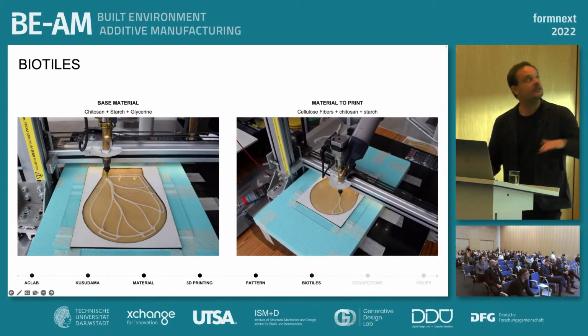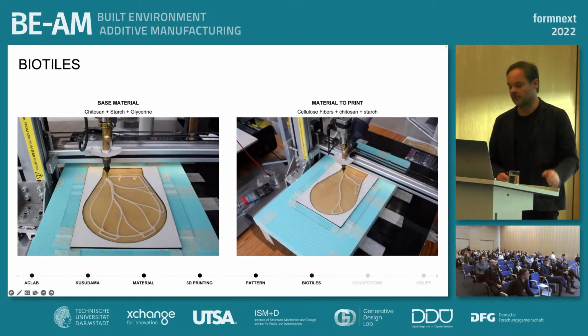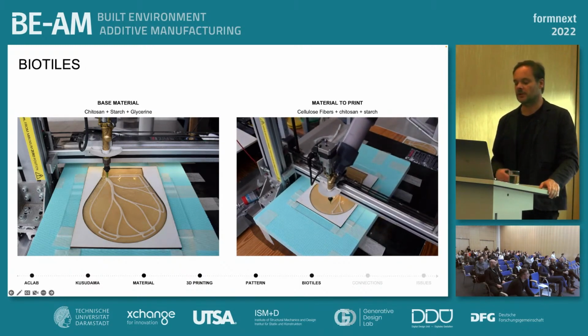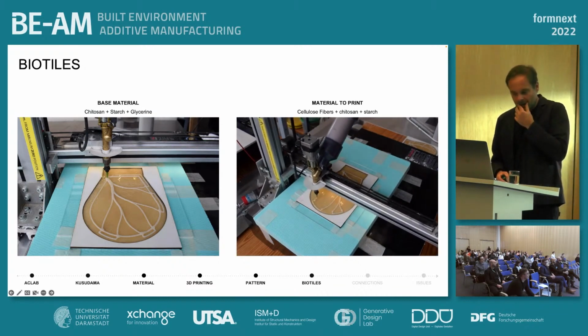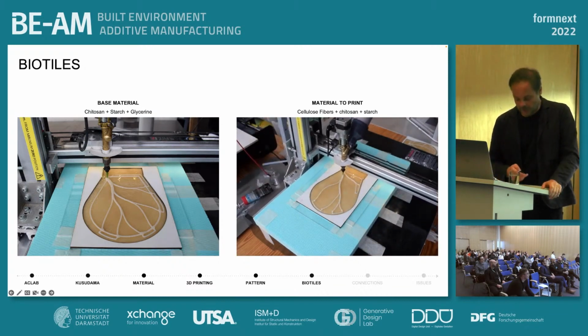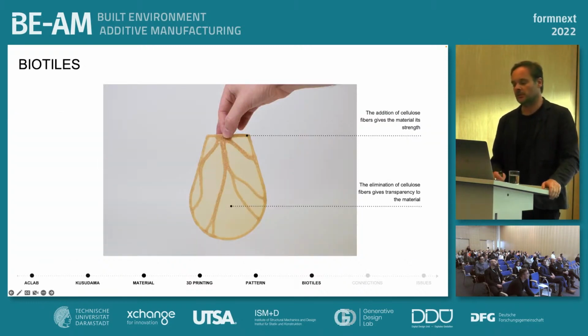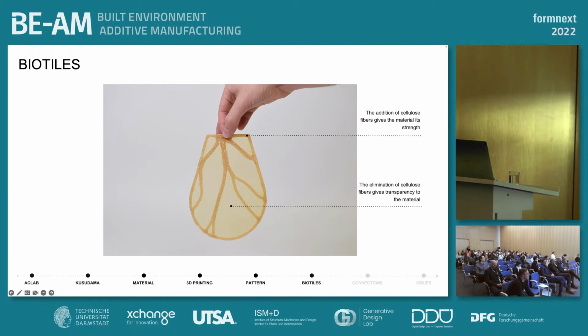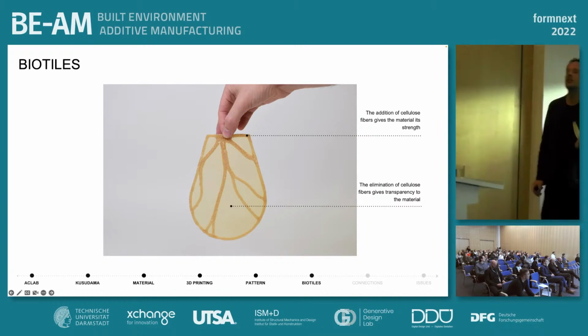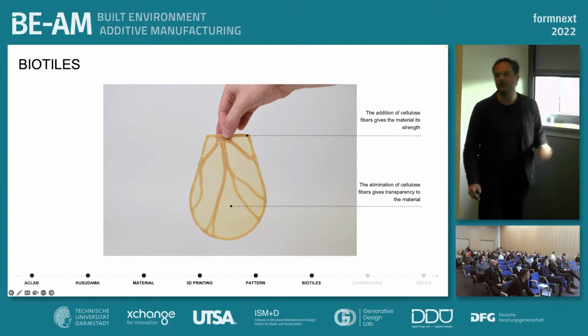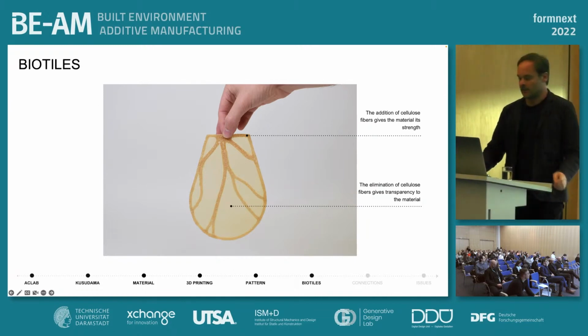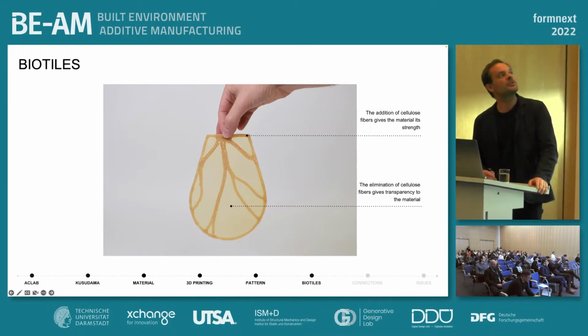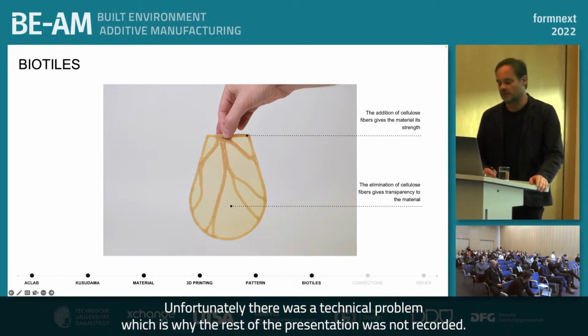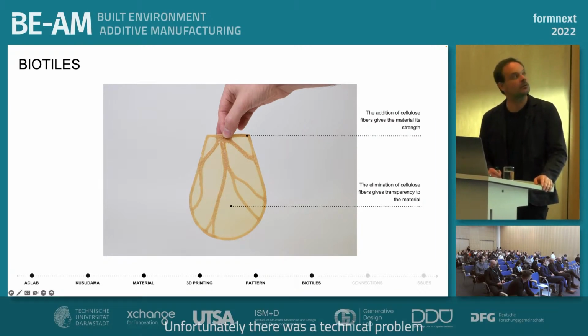And you see here the base with liquid mixture, and then printing the fibrous mixture with cellulose above it. And eventually, when all stages are completed successfully, the membrane looks homogeneous and semi-transparent. Actually, I brought a few samples that I'm leaving here. If you want to look at them during the break, please do. And so we have this homogeneous look with semi-transparency, and the printed areas with the granular finishing.